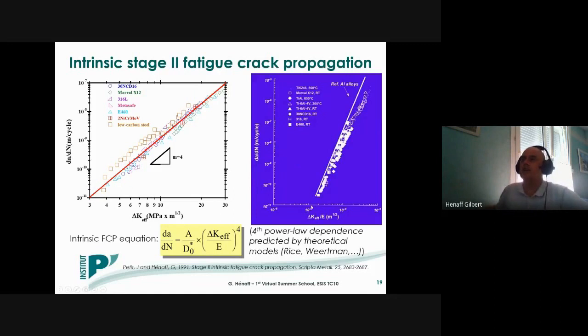You have the crack growth rates expressed as a function of the parameter delta K effective divided by the Young's modulus, which you can assume to be the strain intensity factor instead of the stress intensity factor. And again, you can see that we have almost a unique relationship for these different types of materials, steels, titanium alloys, aluminum alloys. And so we propose to describe this intrinsic relationship by this equation, accounting for the fourth power law dependence with respect to this parameter. And it is noteworthy that this fourth power law dependency can be predicted by different theoretical models that you can find in the literature.